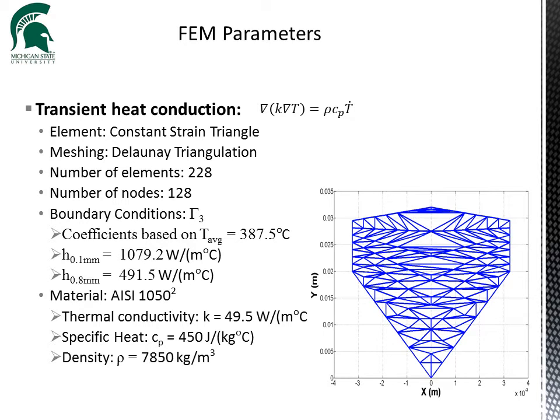Now, the parameters used in the study are a constant strain triangle mesh using Delaunay triangulation with 228 elements, 128 nodes, and a gamma 3 boundary condition, where an average temperature is used for the convection coefficients, where the average temperature is based on the initial and final temperature of 387.5 degrees Celsius, where these are convection coefficients for the edge and the remainder. And we also use steel for the cross-section material.